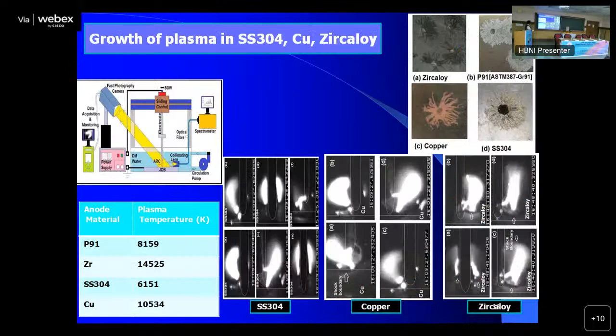So this is the way the crater looks like when you do just one crater formation. This is a stainless steel. This is in P91, which is the material which was chosen for the test blanket module mock-up. This is in zircaloy and this is in copper. So the appearance of the craters are different because the material property is different and the energy imparted to these processes are also different. So the temperatures generated during this process are listed here. 8,000, 14,000, 6,000 and 10,000. So there is melting and even there is evaporation. Quick melting and quick solidification and removal of material all taking place together.